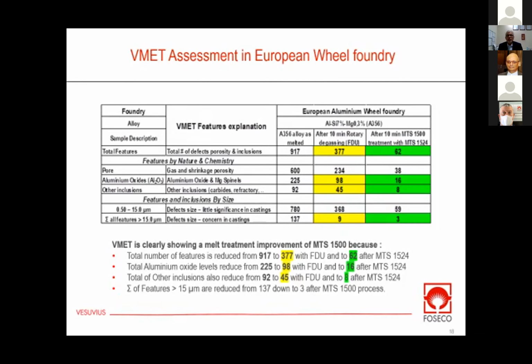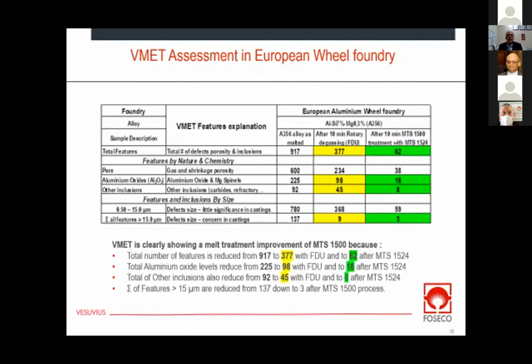When we went one step further and applied our MTS technology to this foundry, that's the green column, you can see an even further improvement. The MTS has taken the melt treatment one step further, and you can see how the total number of defects is reduced, and how the total number of oxide and inclusion is reduced.